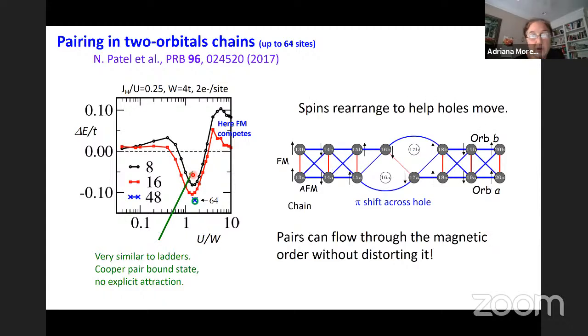So how do the holes arrange in the ladder? We found it interesting that the holes arrange in a way that tries to disturb the magnetic order as little as possible. This is actually not a real ladder - it's a chain where I'm plotting the two orbitals at the same site. So this is one site, these are the two orbitals.